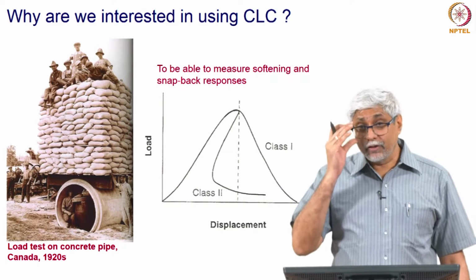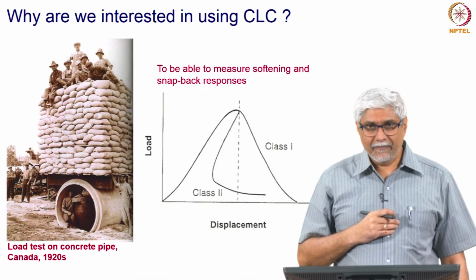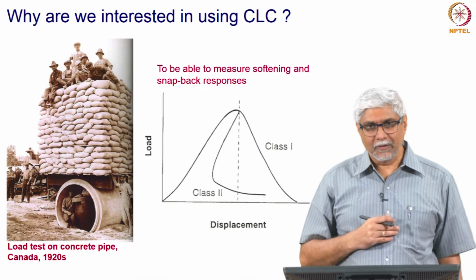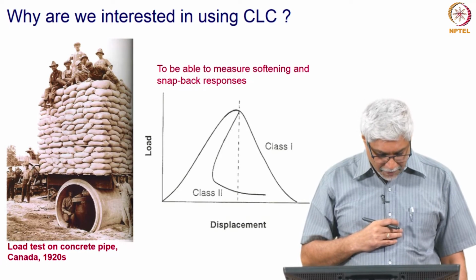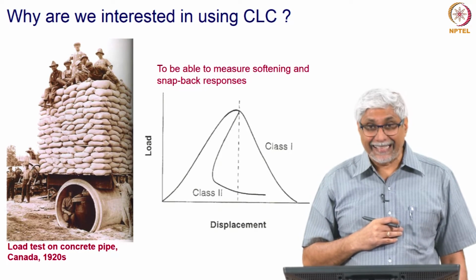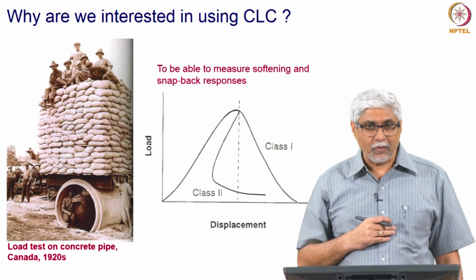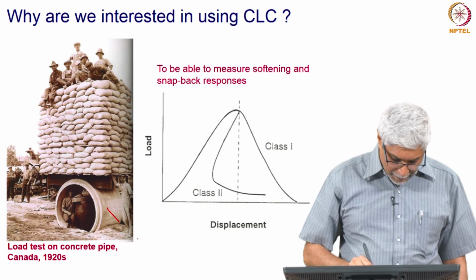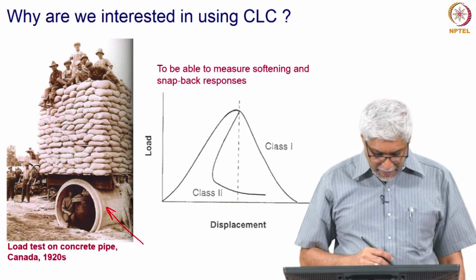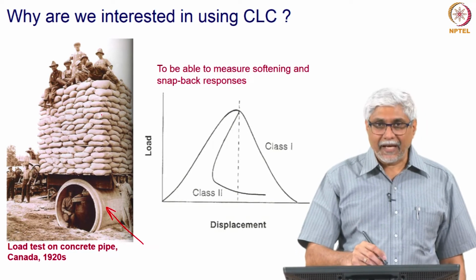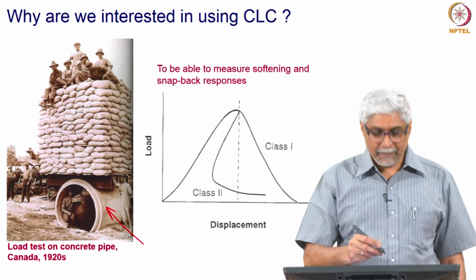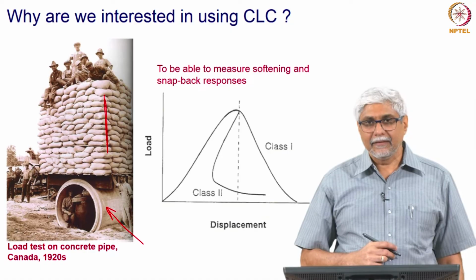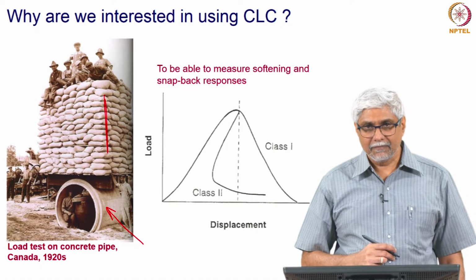Now, why do we have to go to all these lengths? Traditionally, or long back, even now also, we do some load tests like this, which you can see in this image from the 1920s. This is how they tested a concrete pipe. You see here the concrete pipe that is being tested, and weight is applied. You keep on applying weight like sandbags until the load carrying capacity is reached.